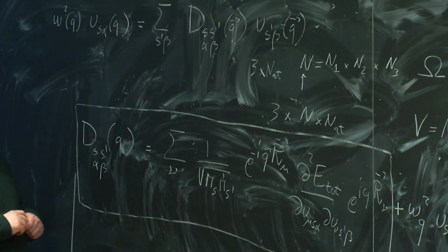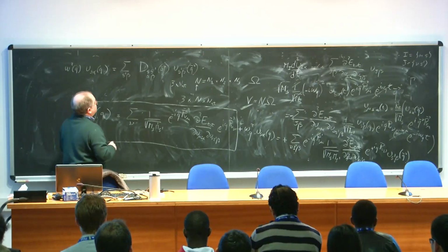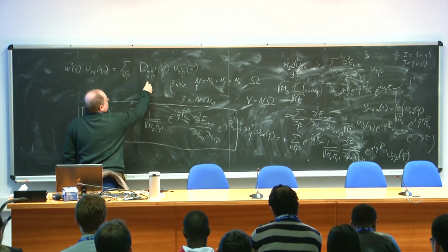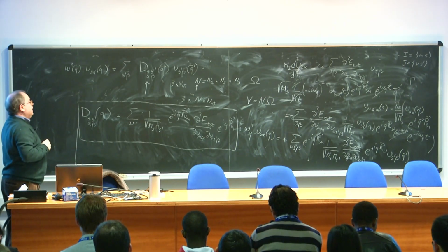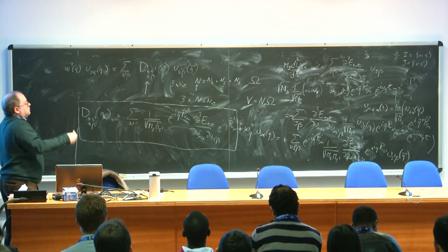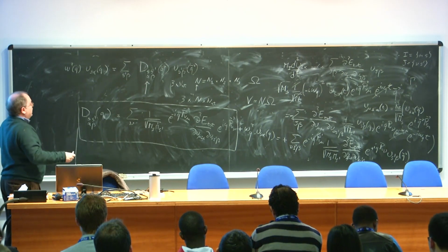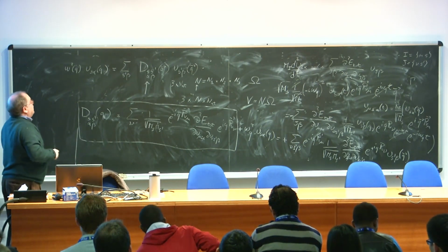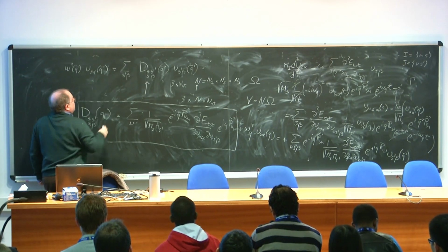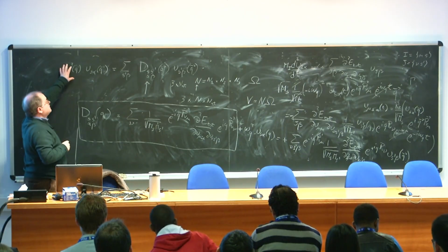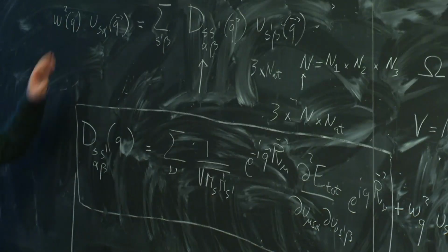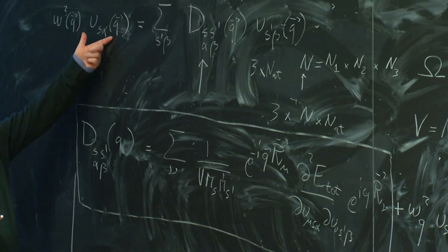So basically the program of today is this. With density functional perturbation theory, we find an expression for the dynamical matrix. We have to do it once we have chosen a Q vector, a wave vector, and then we diagonalize this dynamical matrix and find the frequencies as a function of that wave vector Q. And in principle, we also have the eigenvector of the dynamical matrix.